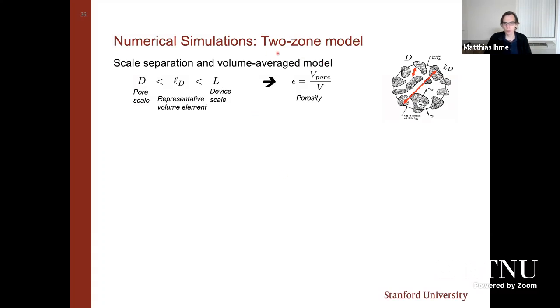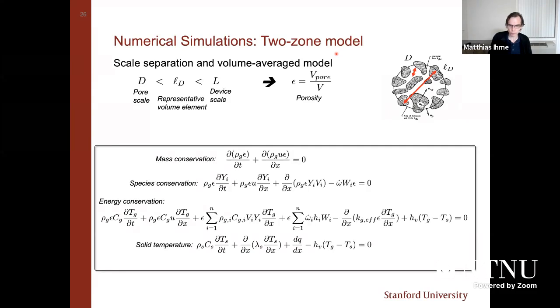We're using a so-called two-zone approach, which essentially takes advantage of the scale separation between the pore size and the flow path. With this, we can write down a set of governing equations. I don't want to scare you here, but I assume that many of you are familiar with this formulation. This is a one-dimensional model, so we are essentially describing the conservation of mass, chemical species, and the energy through this porous media in a one-dimensional setting. X is the coordinate along the porous media burner.